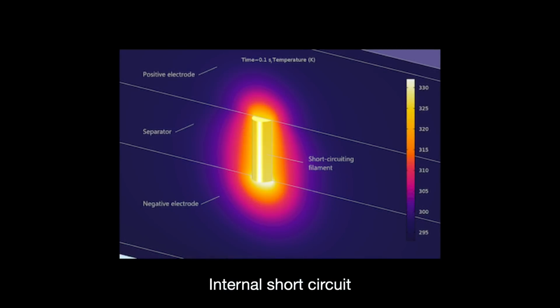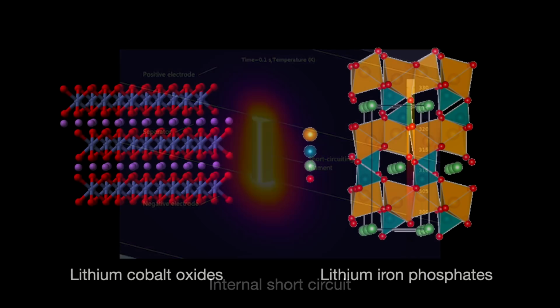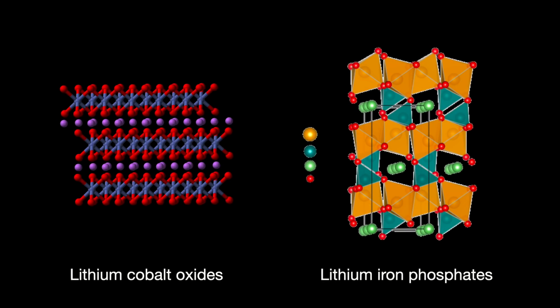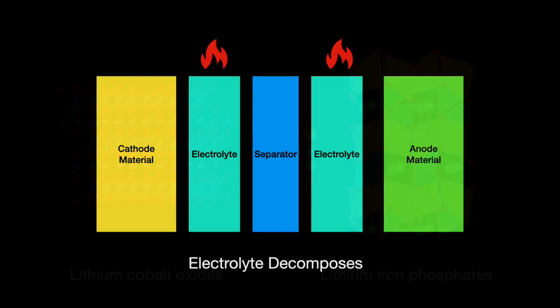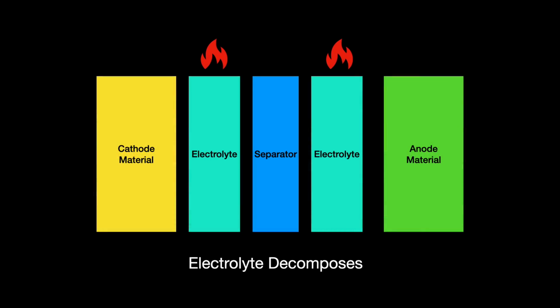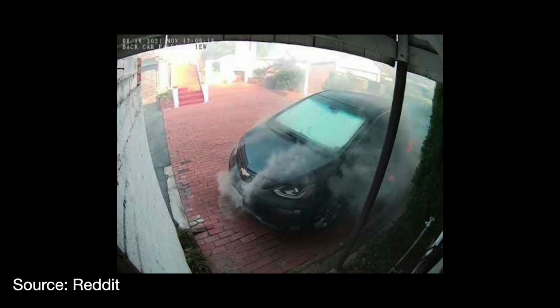The cathode and anode start to decompose, releasing oxygen and yet more heat. Different chemistries of cathodes are more vulnerable to this decomposition than others. Lithium cobalt oxides probably most so, lithium iron phosphates probably least vulnerable and thus tend to be the most safe, but with different drawbacks of their own. When the temperature gets over 200 degrees Celsius, the electrolyte also decomposes, releasing its own heat. Critically, the decomposition releases reactive and potentially explosive gases like carbon dioxide, hydrocarbons, and fluoride gases. By now, every part of the whole battery is breaking down and the car is likely on fire, a fire exceptionally difficult to put out.